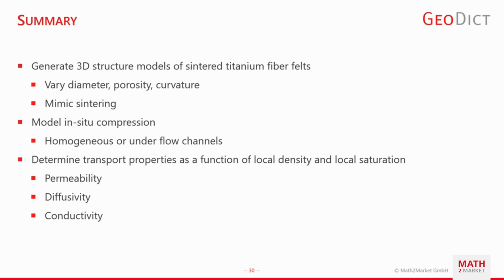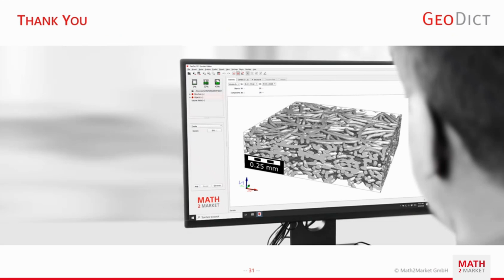So in summary, I've shown you how to generate a 3D structure model of a sintered titanium fiber felt. You can of course vary diameter, porosity, curvature. I just made one quick example of a structure that looks somewhat realistic. It's not some specific structure. I've shown you how you could use GeoDict to mimic sintering. I've shown how you can model in situ compression. You can do that homogeneously or with this flow channel pattern, and then how you can determine transport properties as a function of the local density and local saturation. And of course, you cannot just do that for permeability. You can also do that for diffusivity or conductivity. Except that conductivity maybe is not so much dependent on saturation. And with that, I thank you for your attention.